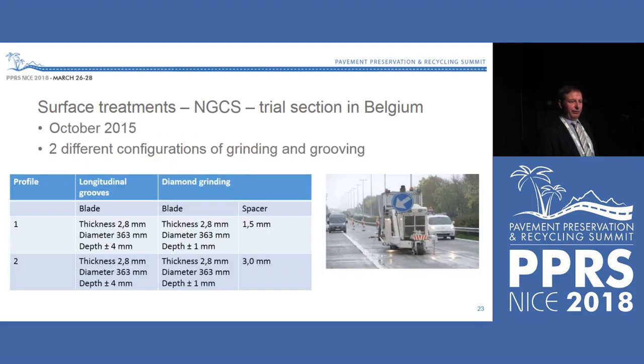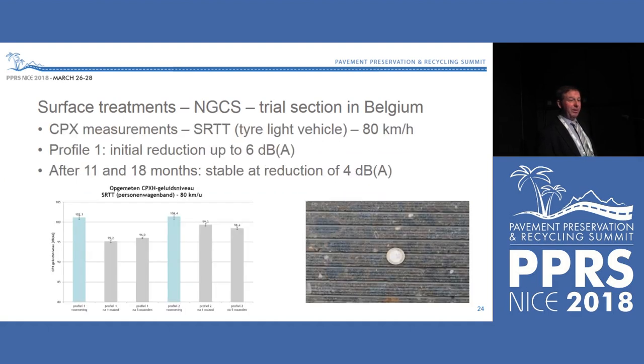And we used two different configurations of this combination of grinding and grooving, always in the longitudinal direction. And so the grooves are 4 millimeter deep, the grinding is 1 millimeter deep, and you can see the difference between the two configurations was the spacer. In the first one, 1.5 millimeter, in the second one, 3. Let's go immediately to the results.